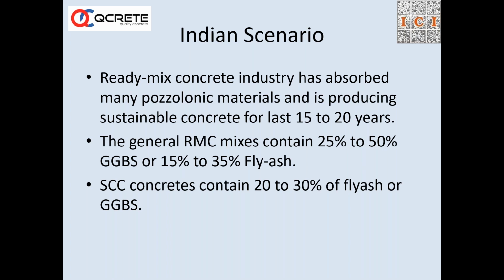And one of the most significant contributions, I can say, by the ready-mix industry in India, from 2000 to 2022, the last 15-20 years, is a good increase in the usage of pozzolanic materials, especially fly ash and GGBS. You can see most of the ready-mix companies are using either GGBS or fly ash, and we have the modern concretes which have been absorbed by the ready-mix concrete industry, which is having a positive impact on the rate of construction and quality of construction. There is also a significant usage of industrial waste like fly ash and GGBS.